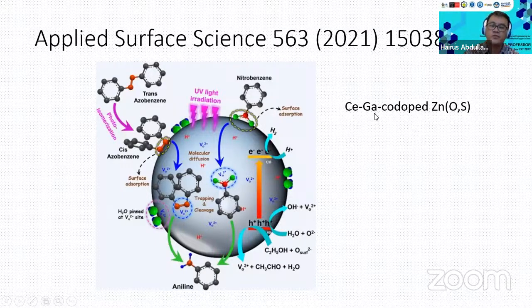After doping these two metals into the Zn(O,S), the oxygen vacancy on the catalyst basically improves, right? Much improved. Because of this oxygen vacancy, some of the polar part of the molecule can attach on the surface, and this will increase the adsorption. Of course, the reaction will be improved also. That's why it's very effective for the chemical reaction.